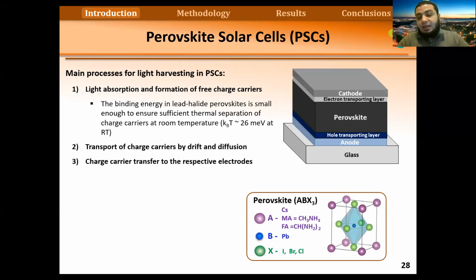So the perovskite material is a completely different class, and in the solar cells it works with a slightly different mechanism. For this material, we have a low binding energy. For organics, we said that we have a high binding energy. It means the electrons and holes are bound together, and it's difficult to separate them into free electrons and holes. But this material has a very low binding energy. At room temperature, the thermal energy is sufficient to form electrons and holes, free charges, without the need of having a donor material, an acceptor material and an interface.